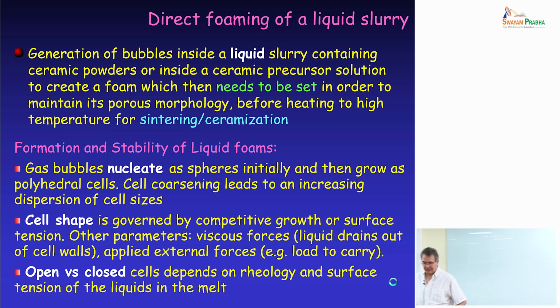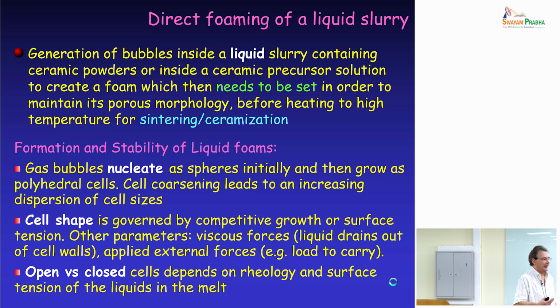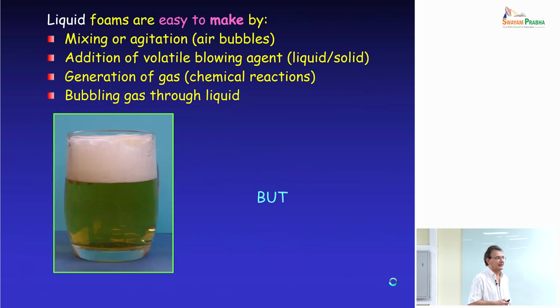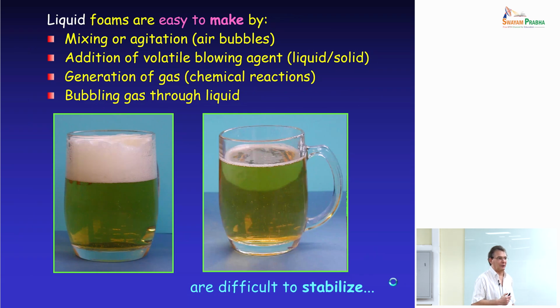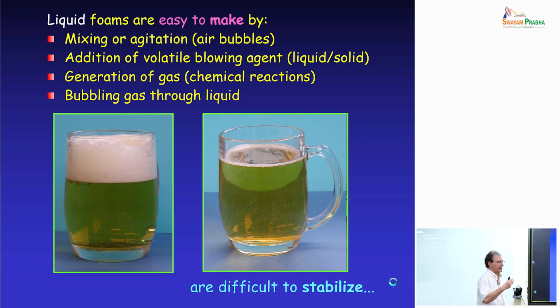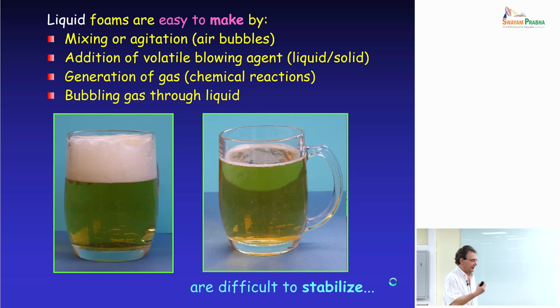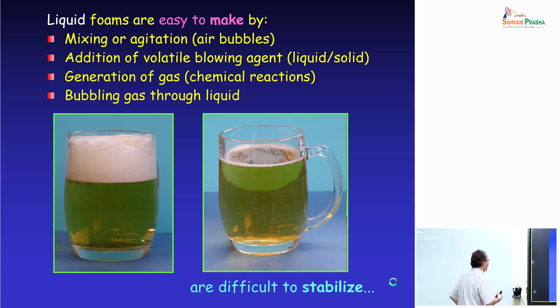Another way of making foams is direct foaming, and this is typically carried out, for instance, for polymeric foams. It's quite a straightforward approach, but you have to realize that making foams is not simple, because you have problems with stabilization of the liquid foam. You have different processes that lead to the disappearance of the bubbles inside your liquid foam. We are interested in liquid foams because after having the liquid foam based on a liquid, water for instance, containing our ceramic particles and gas, then you can consolidate the liquid and obtain your solid foam that can be sintered.